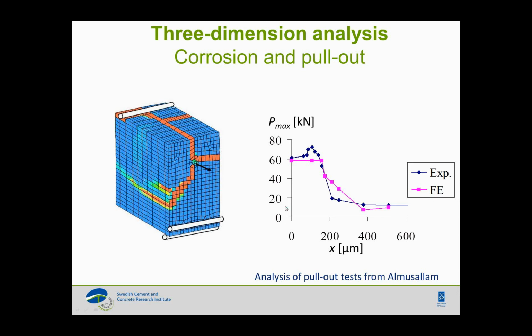And now we are looking at some of the results. Here we are looking at the pull-out force on the reinforcement, and on the horizontal axis we are looking at the corrosion penetration. The blue line corresponds to the experimental findings, where we have a little bit higher bond capacity or anchorage capacity in the beginning, when we have small amounts of corrosion penetration, because before cracking you expect a little bit higher bond due to higher confinement from the expansion of corrosion. But as soon as you have cracking, the force or the bond drops very rapidly. How rapid this drop is depends on how much confinement you have in terms of concrete and transverse reinforcements.